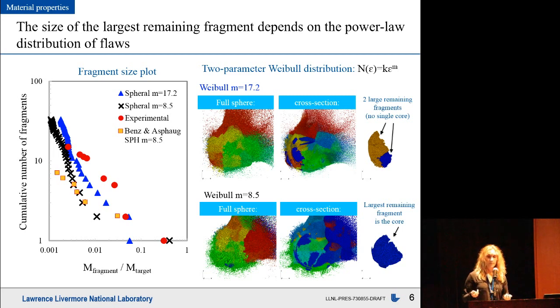To do this, we employ the two-parameter Weibull methodology to see the experimentally determined statistical distribution of flaws into our target material, where K and M are material parameters that are determined experimentally for a specific material. So simply put, by using this two-parameter Weibull methodology, Spheral is implementing flaw distributions into our basalt target material to better represent what we would realistically find in a basaltic rock.